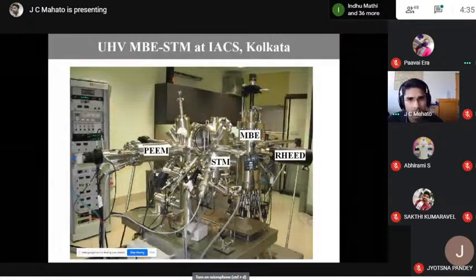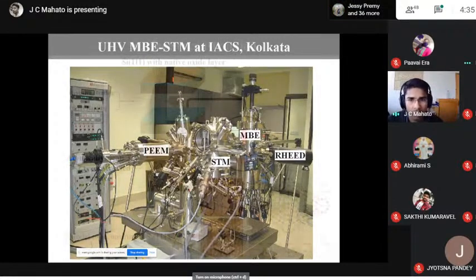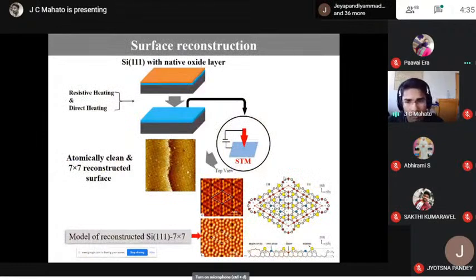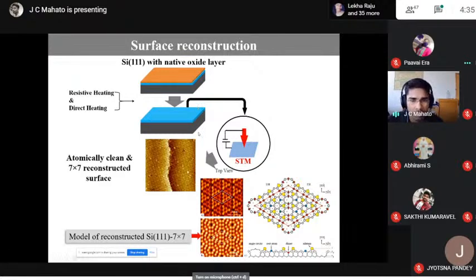So we have investigated this at IACS Kolkata in this MBE STM system. So for the growth, we have chosen silicon wafer. So silicon wafer, as you know, possesses an oxide layer. So first we remove the oxide layer by a standard thermal cleaning procedure. For that we heat the silicon substrate by resistive heating at 500 degrees Celsius for 2 hours. Then pass direct current through it and heat it at 700 degrees Celsius for 14 to 16 hours. And then for 1 minute we flash it at 1250 degrees Celsius.